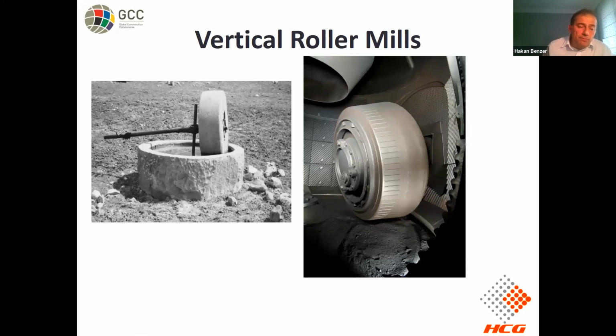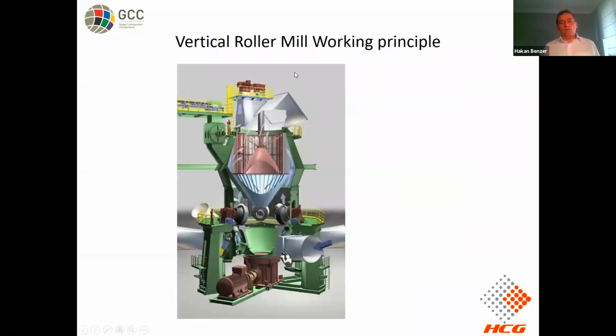So human beings have known this technology since the middle ages, going from muscle power to very strong motor power, which we implemented in the vertical roller milling technology. If you look at the vertical roller mill working principle, we have a grinding table here, and we have the rolls, which apply pressure. With the rotational speed of the grinding table, the feed material coming onto that table is directed underneath the high compression zone, and the air flow pneumatically carries the material to the air classifier on top of the system, which is used for fine classification. The fine material comes out of the system as a final product, and the coarse material is sent directly back to the grinding zone here.